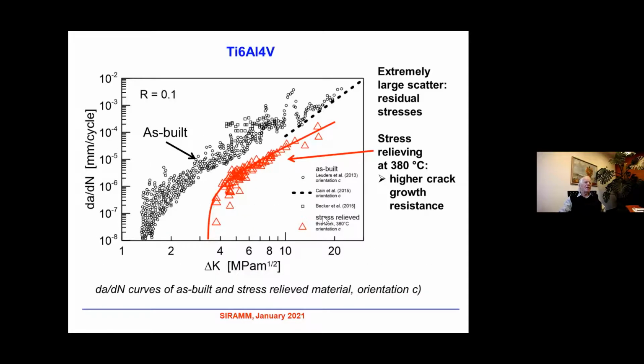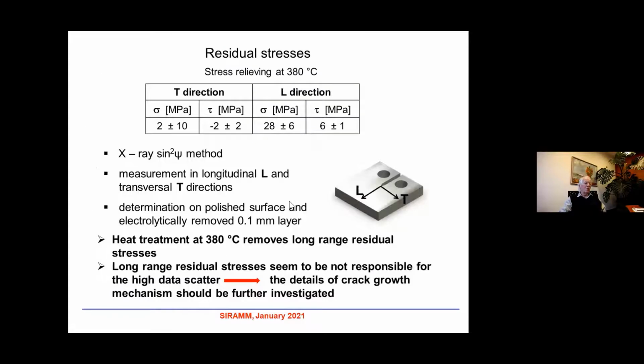What may be the reason? Maybe residual stresses, because the stress relieving is usually done at this temperature. So we performed an experiment and measured the residual stresses in our specimen. You can see the CT specimen, and we measured it in two directions, longitudinal and transversal.